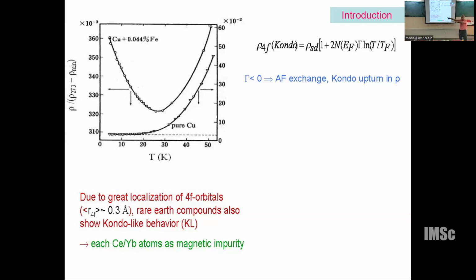Initially it starts with magnetism. I've been telling you, at high temperature magnetism, at low temperature no magnetism. That is where non-magnetism comes. At low temperature, depending on the temperature scale, they found a bound state. Therefore, you start with magnetism and lose it. So that results in the minimum. These are all the important characteristics of the delocalization, localization phenomenon. It was believed that when it comes to rare earths, the 4f orbitals, you find that in 1970, they behave exactly like this. If you look at the transport properties, they behave like copper.